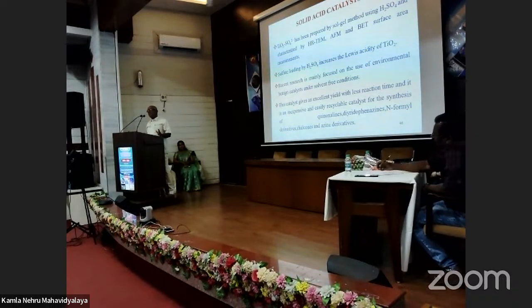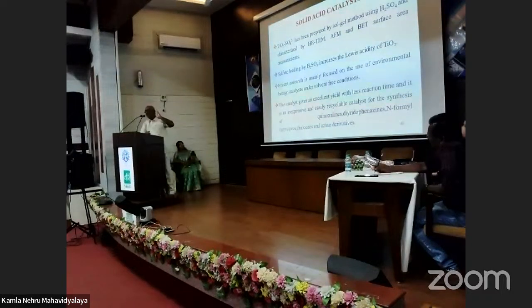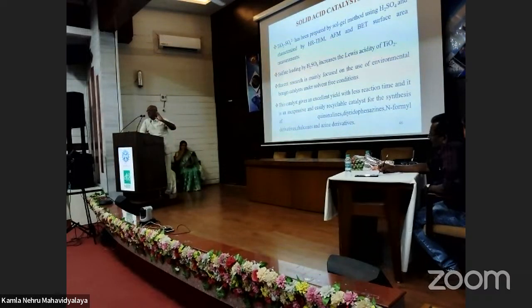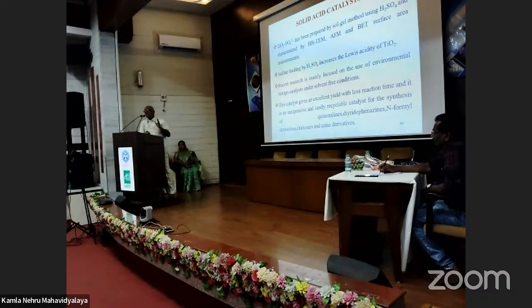And the same catalyst can be used as a solid acid catalyst. Actually, one time we initially prepared a sulfated TiO2 simply by adding sulfuric acid during the preparation of TiO2 itself, and we reported sulfated TiO2 at that time. We prepared it only for the degradation of pollutants, but later we found that the catalyst can be well used for organic transformations, particularly as a solid acid catalyst.